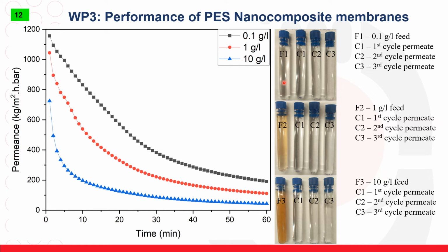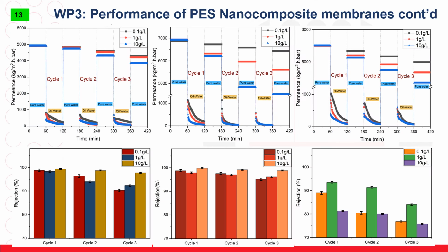And we checked the membranes for different cycles, and for each cycle, pure water came out of the membranes. We checked the performance of the prepared membranes over 3 complete cycles. We started with pure water, then subjected the membrane material to oily wastewater, used pure water again, then oily wastewater again, pure water, and oily wastewater again for the 3rd cycle. And we did this using 3 oil concentrations for the 3 membrane samples prepared.